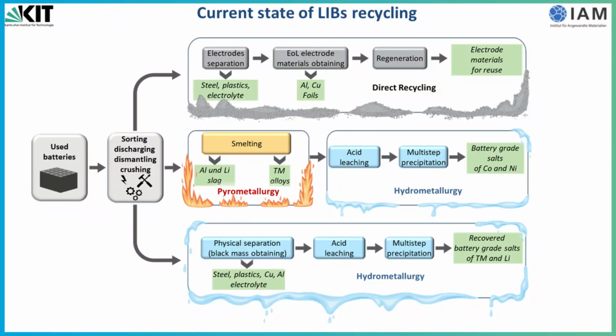After the pretreatment in the pyrometallurgical methods, all battery constituents are smelted at really high temperatures of more than 1000 degrees C. As a result, a transition metal alloy is obtained, while lithium, aluminum, and graphite are lost in the so-called slag or gas evaporations. The transition metals, which are recovered as alloys, further go through hydrometallurgical methods, through multi-step leaching and precipitation, where their salts or battery-grade salts are created and used for remaking cathode materials.